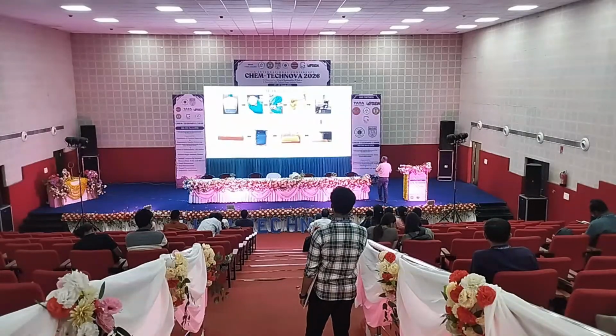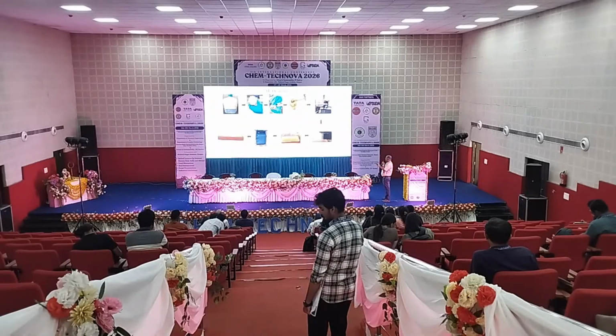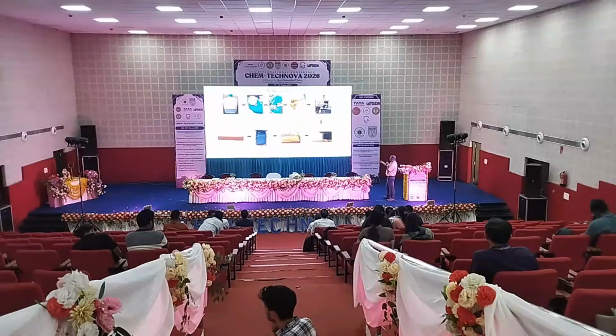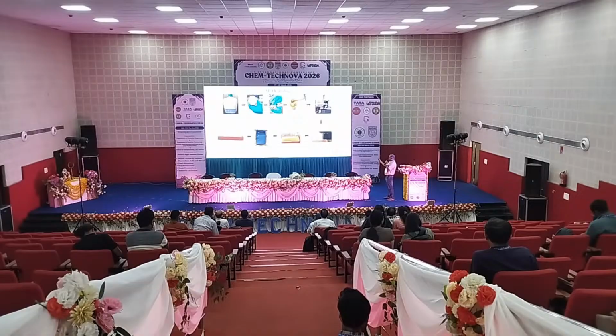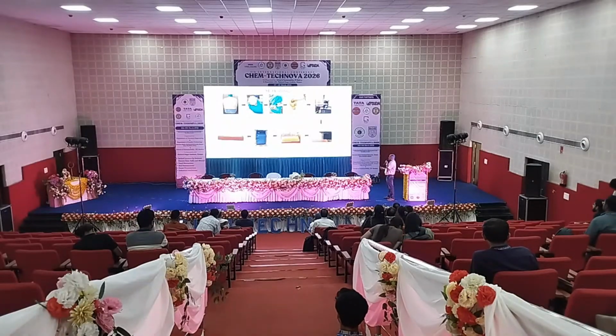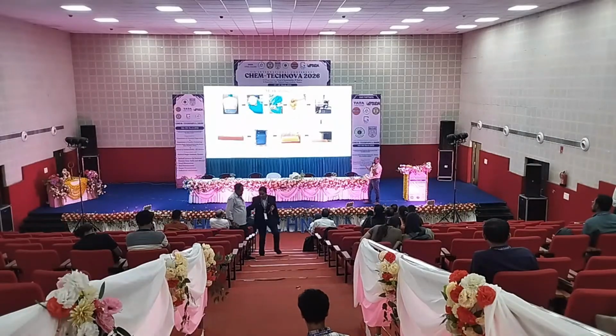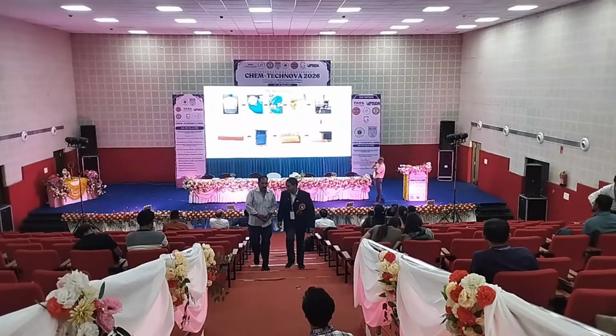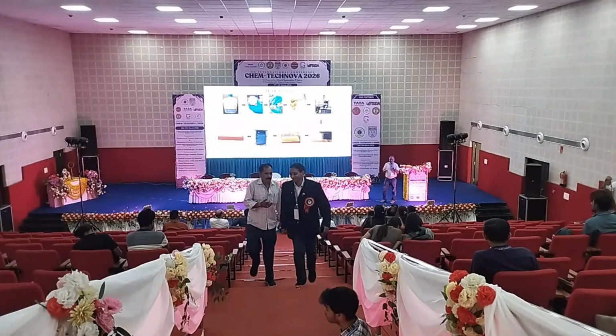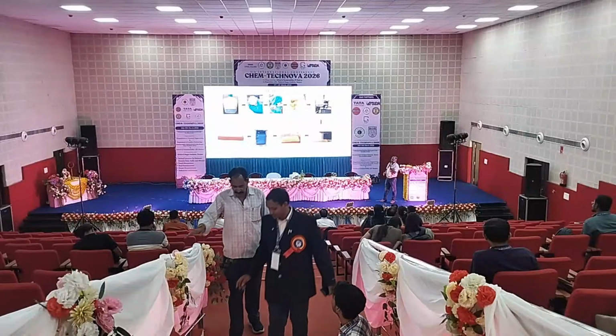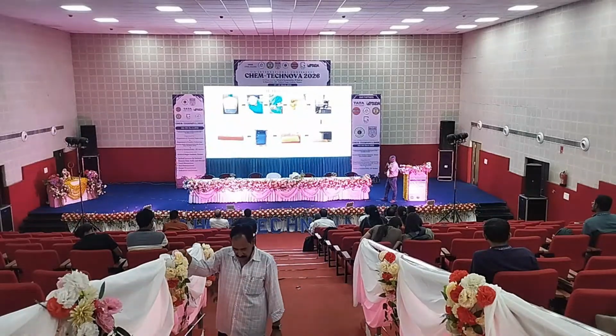So you can see that, first the phenol resin is there. We add nano fillers, and we go to the 3D printer. You can see how it is a direct ink writing 3D printer. With the needle, we do layer by layer addition, and you can make some build volume of the composite product. The thermal shield is there. Then it has to be post cured. It also requires some optimization. Some minimal optimization on curing has been done with respect to application of the bed temperature. Then after that, it has to be post cured in the oven. That will be your final cure.